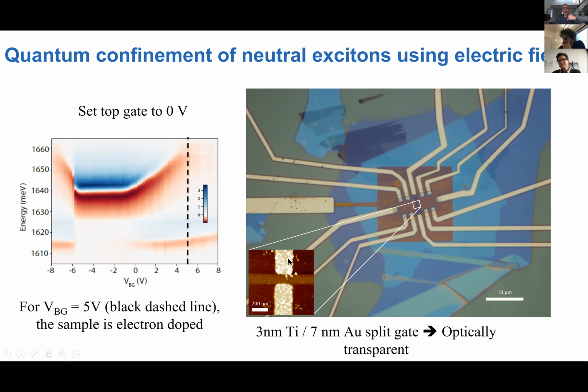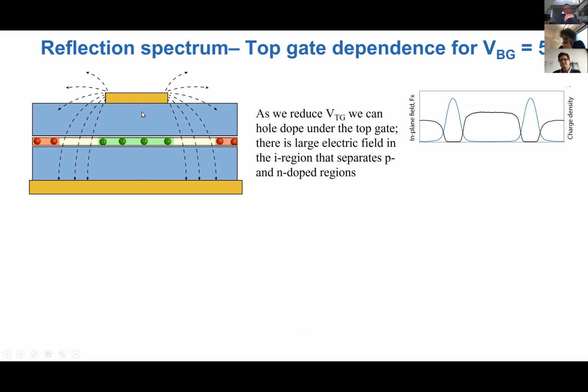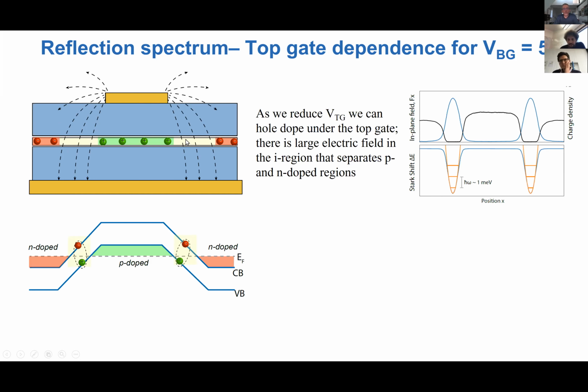Now, what we would expect is that as we make this top gate voltage more negative, such that it's less than minus 5 volts, then we will start doping the material underneath the top gate with holes. Most of the monolayer is electron doped, so we have these n-doped regions, but right under the top gate, we're going to have hole doping, okay? And in between, there is necessarily an undoped neutral region, and it is in this neutral region that we can have bare excitons, right? Now, but these bare excitons actually are subject to a relatively large in-plane field of order 0.1 volts per nanometer.